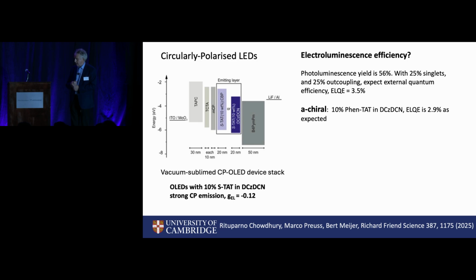And let me start with the achiral material that we've used, which is the Phen-TAT. What we would expect, because this material has a luminescence yield of around 50%, that the external efficiency of photons generated by electron hole capture should be a quarter of 50%, which is down at about 3.5%. A quarter because of the triplet fraction, 3/4. A quarter because only a quarter of photons generated tend to get out in the forward direction. So we should have got 3.5%. We measured 2.9%.